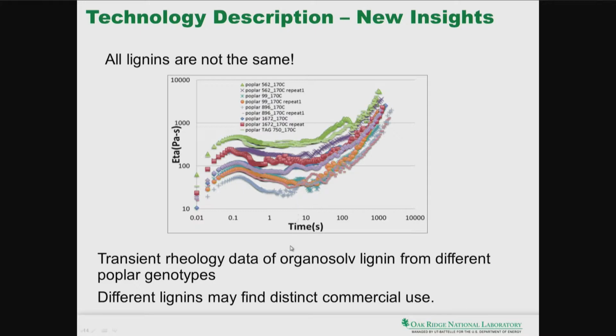And when we did the shear rheological study, and I'll come back to that later on, why we are doing rheology, then you find that the viscosity of the melt, lignin melt, differs by a couple of orders of magnitude, although those are all from hardwood poplar lignin. So all lignins are not same, and if we can understand the chemistry of lignin, we can tailor the product, and that's the message here.